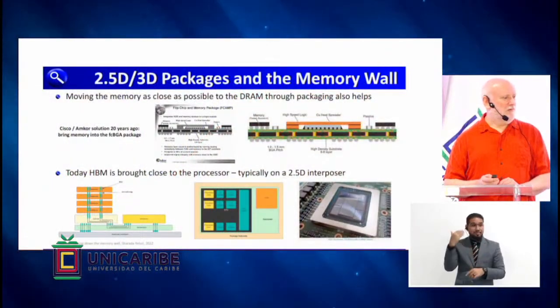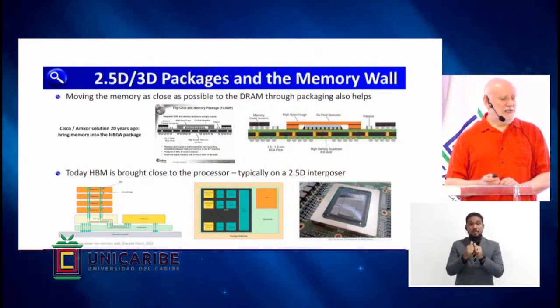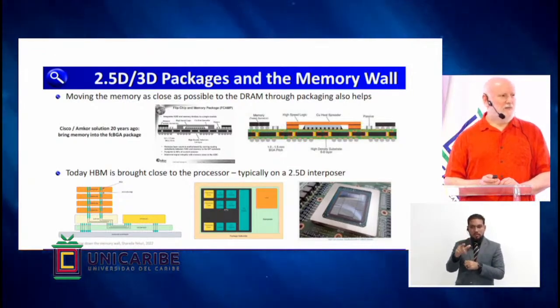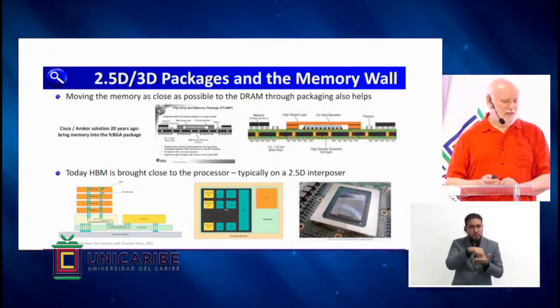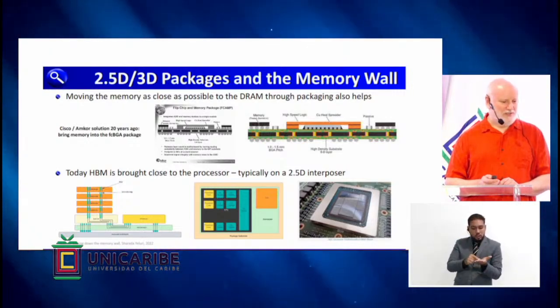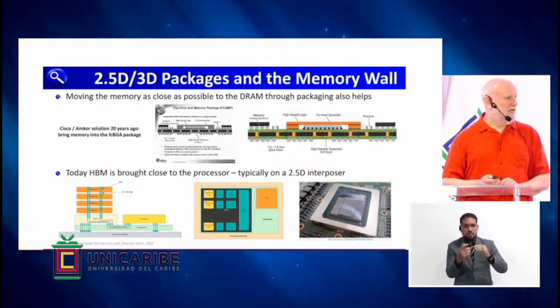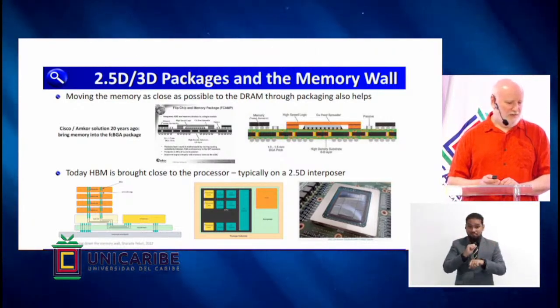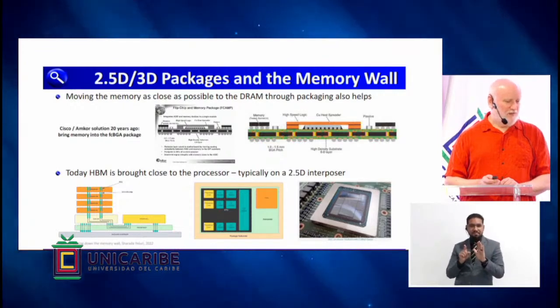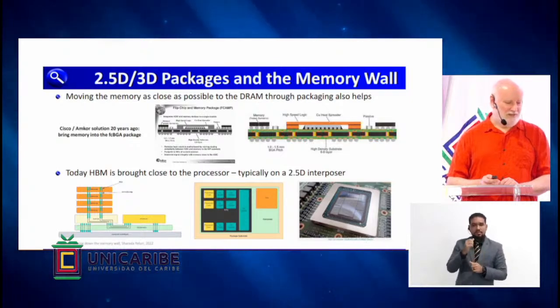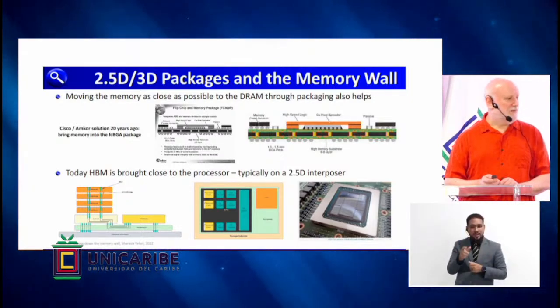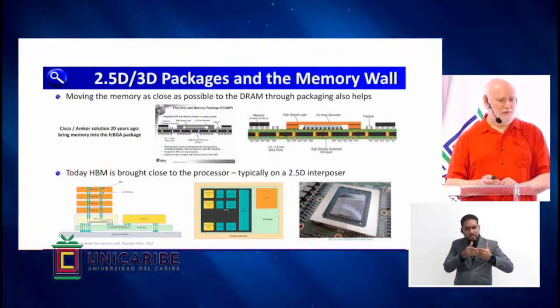One way to do that is to take the memory off the printed circuit board and put it on the package itself. I'm showing one package that we did, going back 20 years when I was at Amkor and we were working with Cisco, who were trying to address this problem. We brought the memory onto the package substrate itself, and it's the same thing that's being done today. But in this case, in the lower right, that's a GPU processor with the memory brought right onto a silicon interposer, so that it's as close as possible and those connection lines from the memory to the processor are as short as possible.